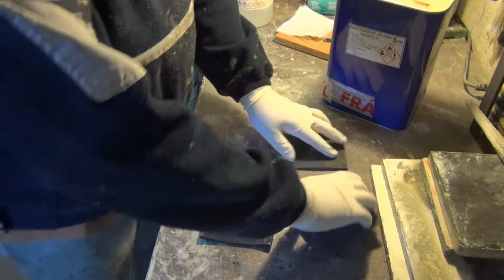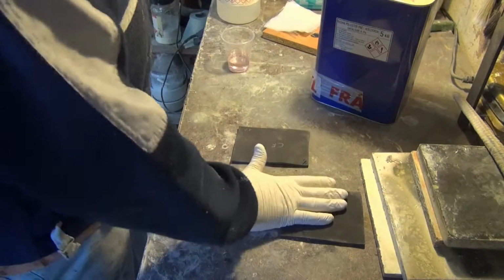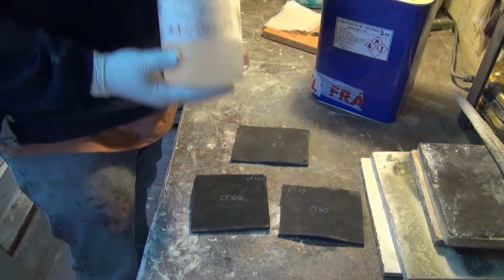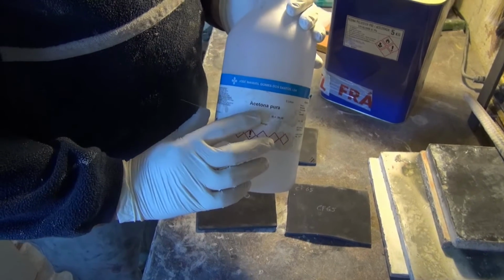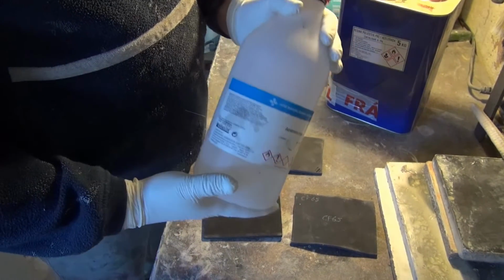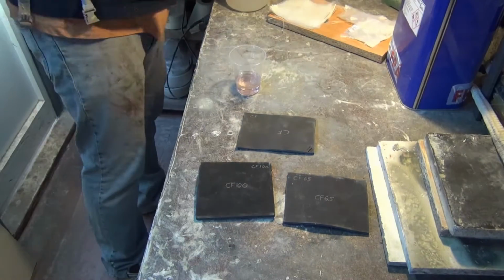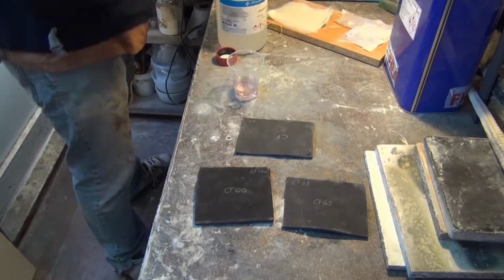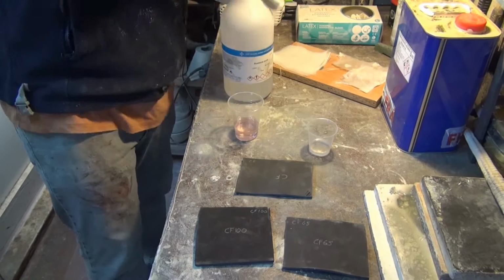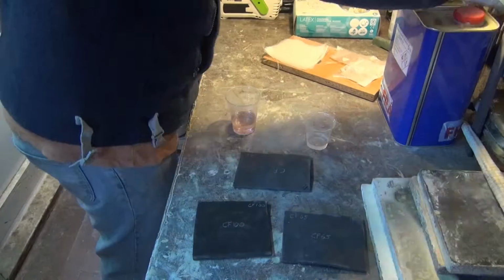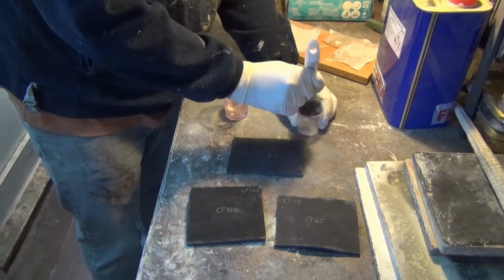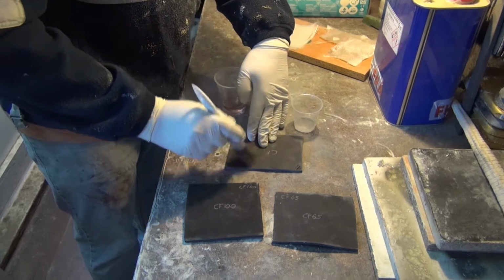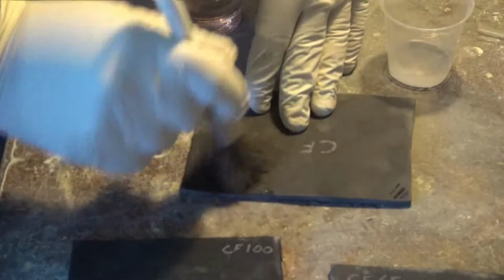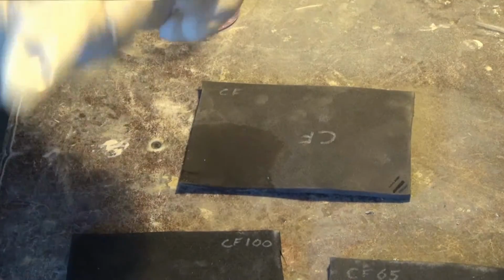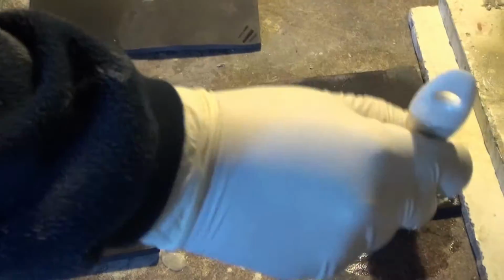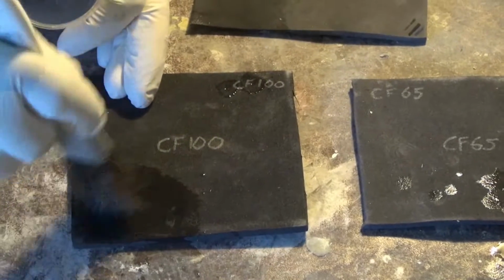The second test was resistance to acetone, to see if it is possible to apply fiberglass and polyester resin. If the foams are not altered in structure and consistency when wet with acetone, then it will be safe to apply the resin. Using a brush, a generous amount of acetone is applied in each of the samples. Then we wait a couple of minutes to see if there are any changes.